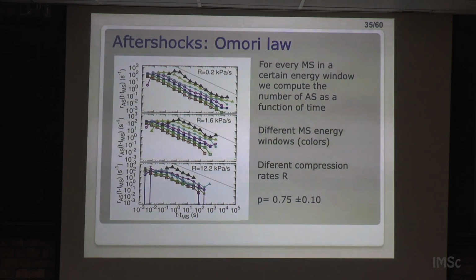Okay, then you can also test the other laws. You can test the Omori law. Now the extra difference here is that we can control the rate. So we have experiments at different rates. And then we have these curves here for the different windows, the different colors, and the three panels are different rates. We get Omori exponents which are not very similar to earthquakes, they are smaller, but this probably has to do with the problem that we are not locating where the events are occurring. We don't have location. So we are considering the whole sample, and then probably what we classify as aftershocks are not really aftershocks. This could be one of the explanations that we are trying to resolve.